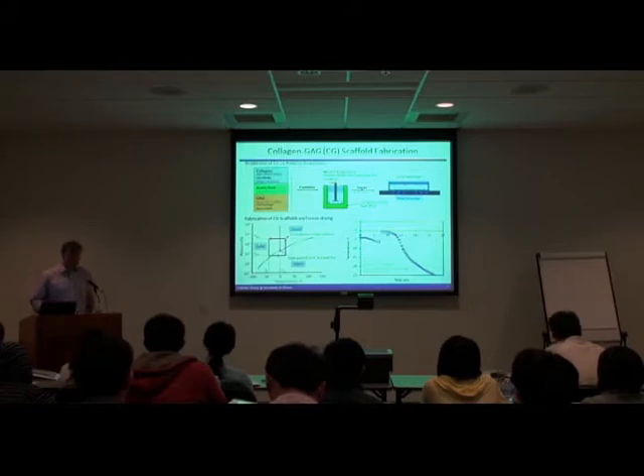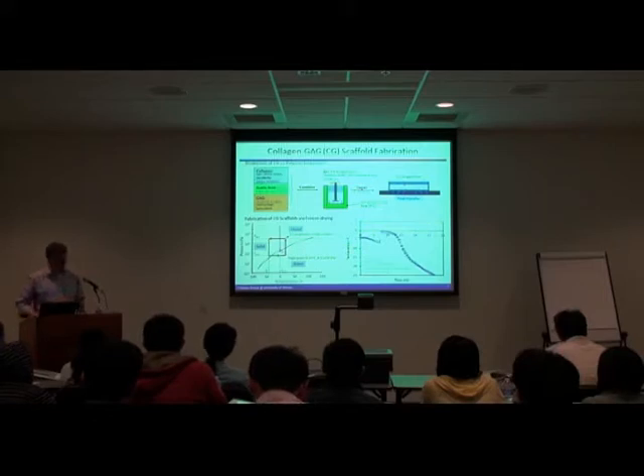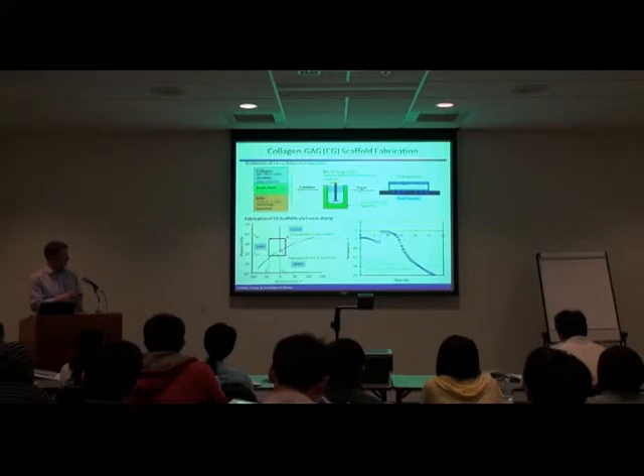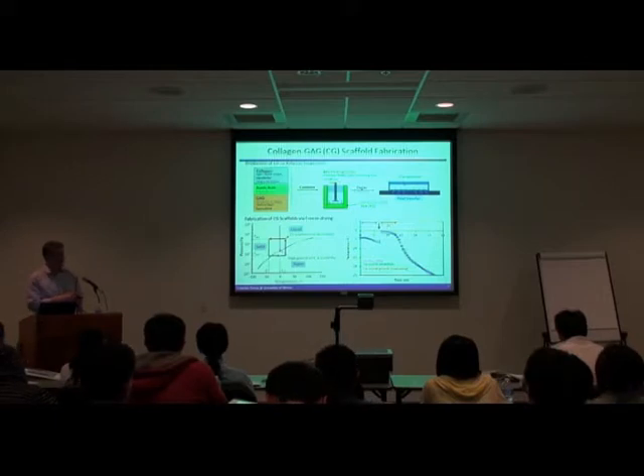And so what we've been able to show is that, as you'd expect for a lot of solidification kinetics, and this is a thermocouple put inside the suspension as it's freezing, you start out with an undercooling phase, and then you have an ice crystal nucleation phase. Then you have a coarsening phase, which is what actually defines the size and shape of the ice crystals. Controlling the thermal treatment at this phase is where we do a lot of our work to change the size and shape of the final scaffold structure. And then there's a cooling phase.